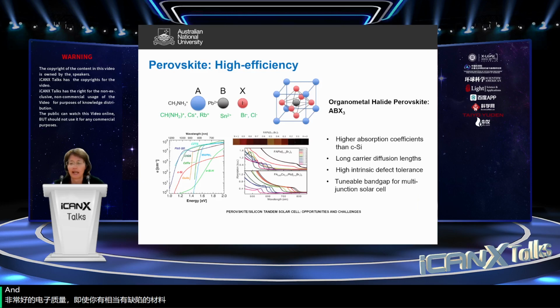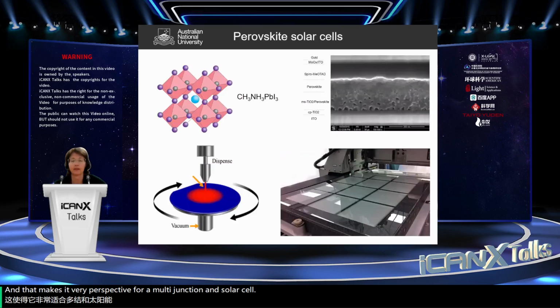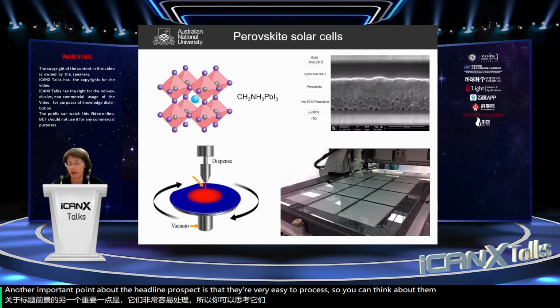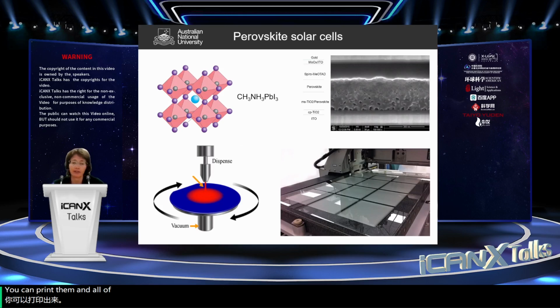And another important point is that you can change the bandgap of the perovskite material by changing the elements that are in the perovskite crystal, and that makes it very prospective for a multi-junction tandem solar cell. Another important point about the halide perovskites is that they're very easy to process. So you can spin coat them, you can print them, and all of this makes them easy and cheap to use.